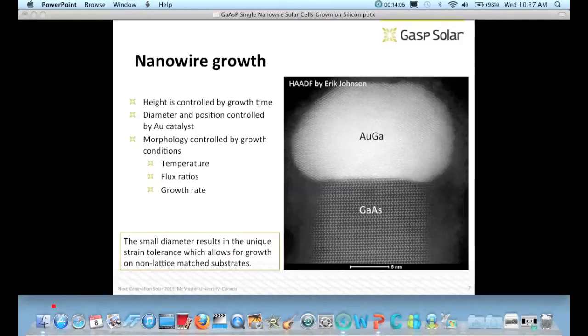And the reason is that this is, as you can see, a TEM image of a gallium arsenide nanowire with a gold-gallium solid droplet on top. It's been cooled now to room temperature. And you can see that this is a wurtzite, cubic wurtzite structure. You have the AB orientation. And if you look closer at this image, you will also be able to see that it's grown in a 111B direction. That is, each of these monolayers terminates in a group 5 atom. It's arsenic, and you have the gallium atom below.